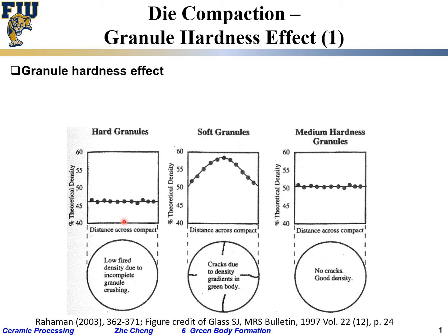You see what I mean? Because they are hard granules and quite often not spheres, they're going to pack relatively uniform but at low density. This is across, let's say, a pellet. On the other hand, if we have so-called soft granules, what people find across a pellet, especially one with a larger diameter, is that in the center it packs denser. Around the edge, where it meets the wall of the die, it has lower packing density.